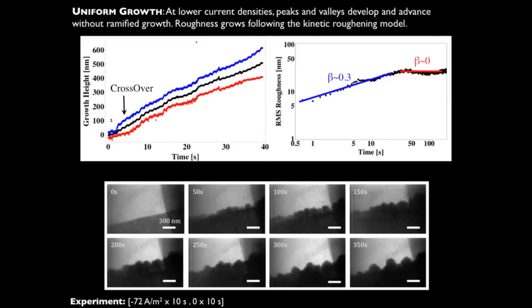Now we have a quantitative measure of what's happened during electrodeposition. We can look at a very long time of a low current density — never reaching the diffusion-limited growth regime. We look at what's happening with the maximum, minimum, and average height as a function of time. We're depositing for 10 seconds and then taking 10 seconds off, so it's actually pulsing. For galvanostatic deposition, the average growth height grows almost at a constant. We can use the RMS roughness as a measure of how wavy the surface is.